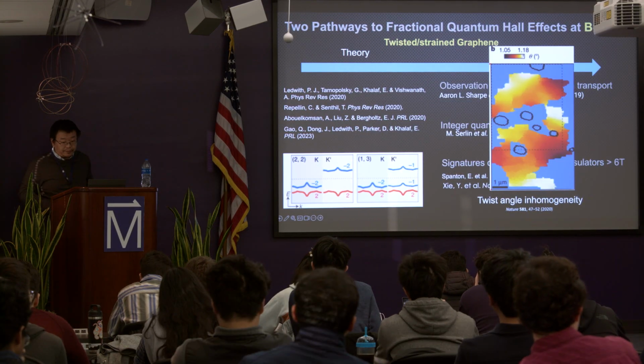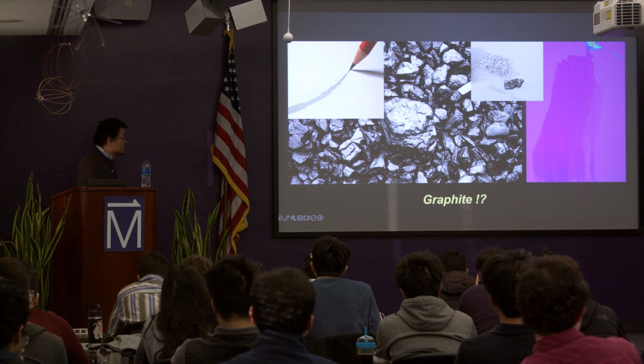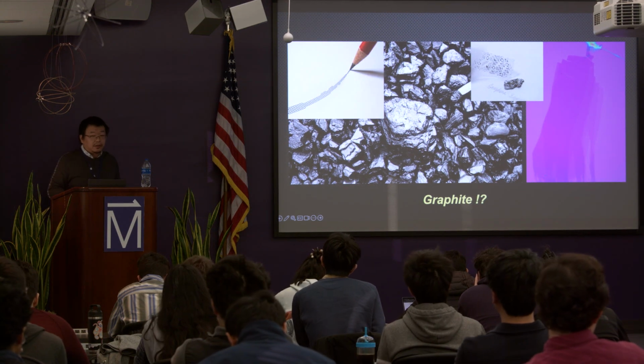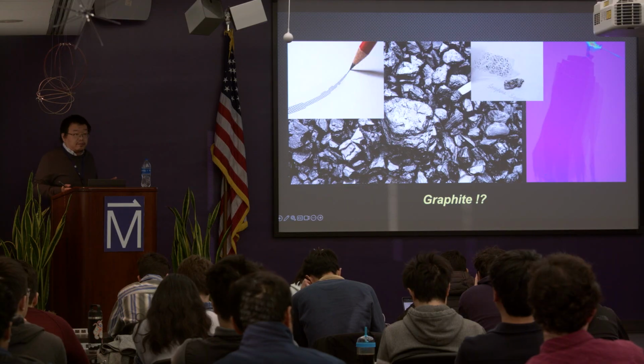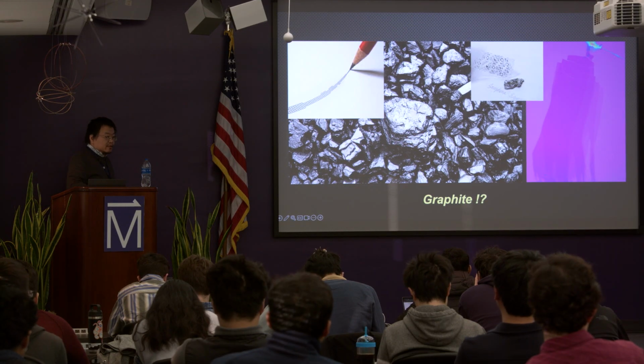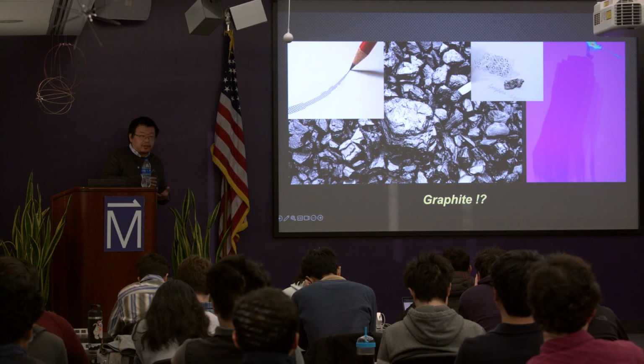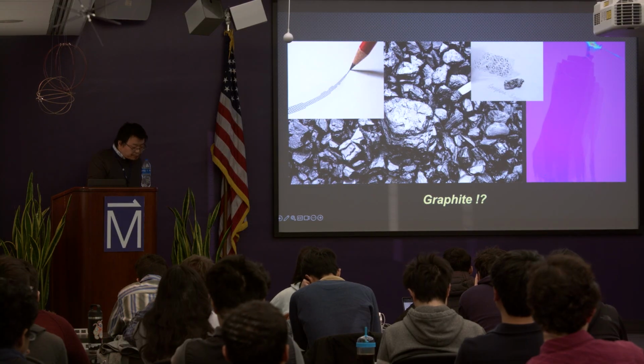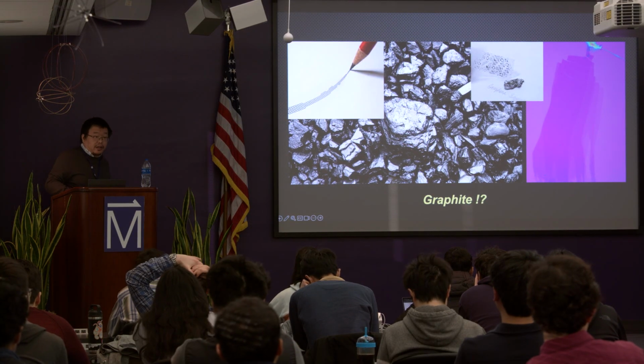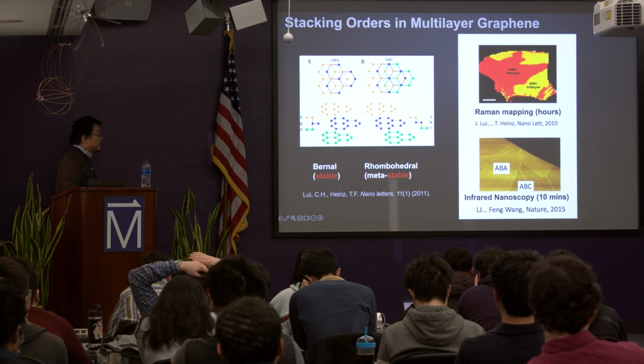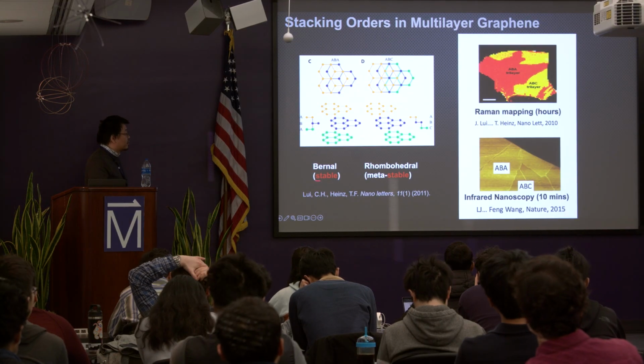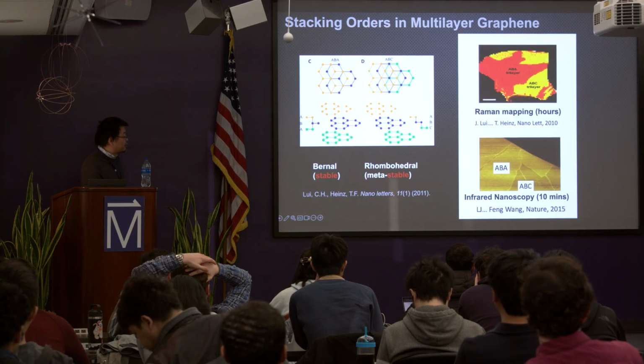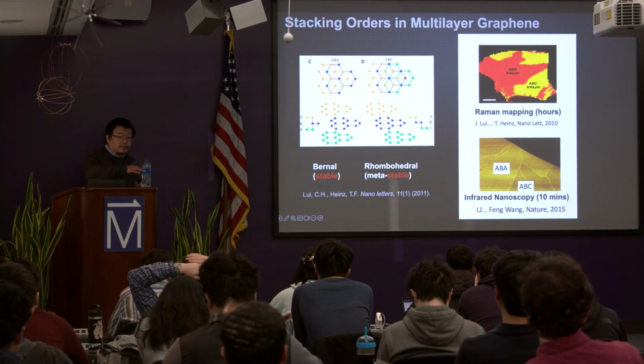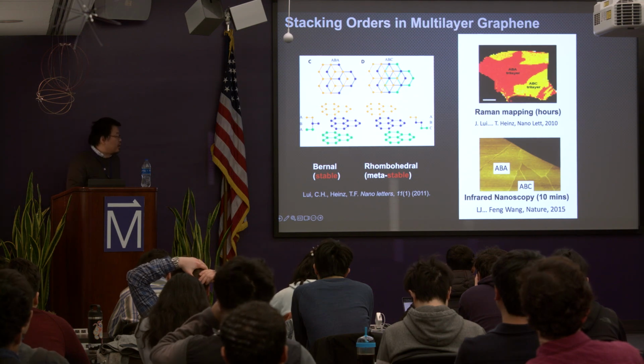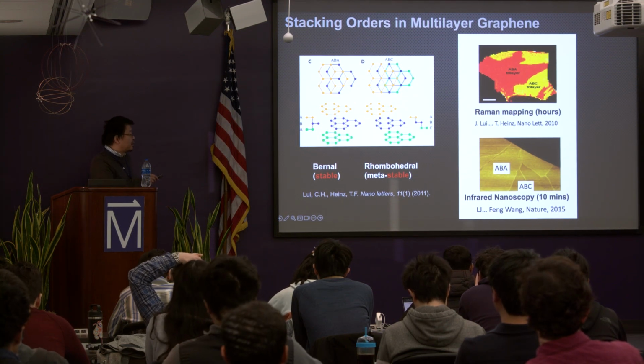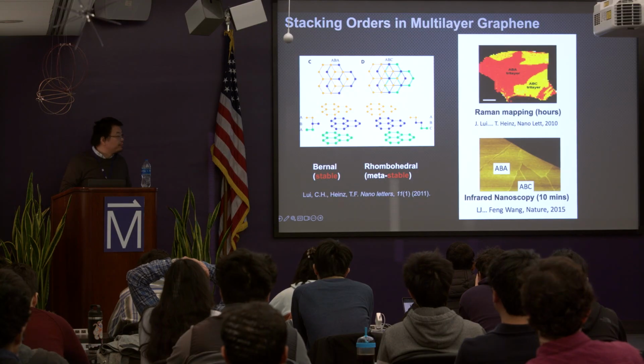So we'd rather go the other road, which is just natural graphite. The sample we are using is a piece of natural graphite you dig from the mining, and you just mechanically exfoliate it, and you get such a flake. And of course, it's not a random graphite, it's with certain stacking orders. You have two kinds of most common stacking order for graphite. One is called Bernal stacking, where you basically stack the sheets back and forth. The other is called rhombohedral stacking, where you keep stacking along one direction, which forms a sort of staircase form.